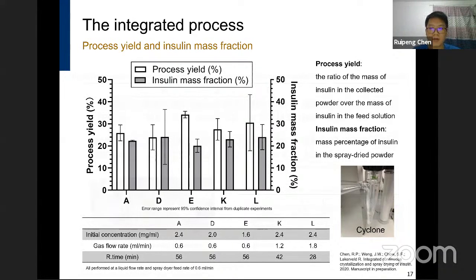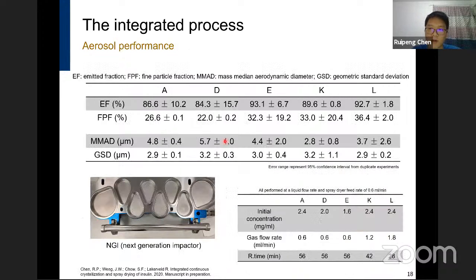So finally, it's about the aerosol performance, which is characterized by the next generation impactor, which can simulate the dispersion of a dry powder from the inhaler to the lungs. Four parameters are used to characterize the performance: the emitted fraction, which is the fraction of insulin that was emitted from the inhaler; the fine particle fraction, the mass fraction of insulin in the optimal size range; and the mass median aerodynamic diameter and the geometric standard deviation, which describe the aerodynamic particle size. For all the test conditions, the emitted fraction is around 90%, which is good dispersibility of the powder.